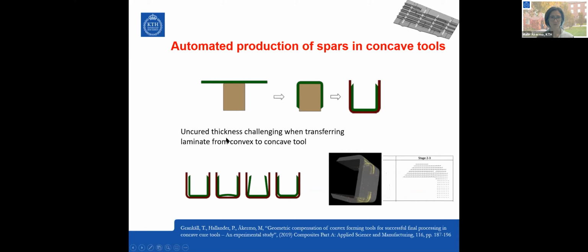However, the uncured thickness, if you lay up a lot of materials like this in the ATL or AFP, there is a bulk factor that is remaining after forming, which when you put it into the female mold, needs to be taken into consideration. First of all, these steps from flat layup to putting it up on a convex mold is simple.